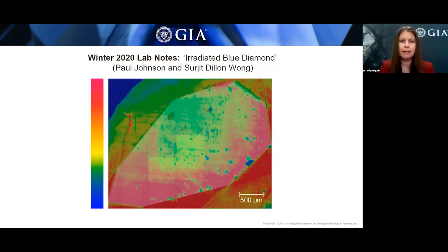This GR1 radiation damage, along with the spectroscopy and the gemological features, allowed the authors to confidently determine that this diamond had been artificially irradiated to create the blue color. Nevertheless, it contained gemological features that were consistent with natural pink type 1A diamonds. This included very strong graining and glide planes that had a pink color.